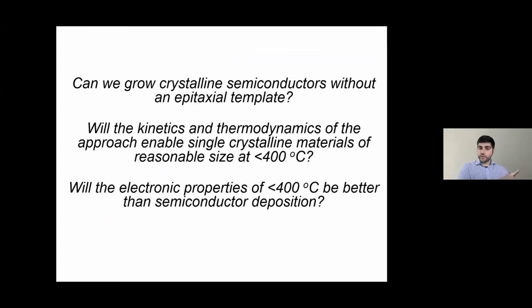First, can we grow crystalline semiconductors without an epitaxial template? Can the kinetics and thermodynamics of this growth allow us to make materials with reasonable performance at temperatures below 400 degrees C? That temperature limit exists because if we have a fabricated silicon CMOS wafer, we can't process it at temperatures above 400 degrees C for too long. This thermal budget really limits the temperatures and times you have access to if you want to build on top of a fully fabricated wafer.